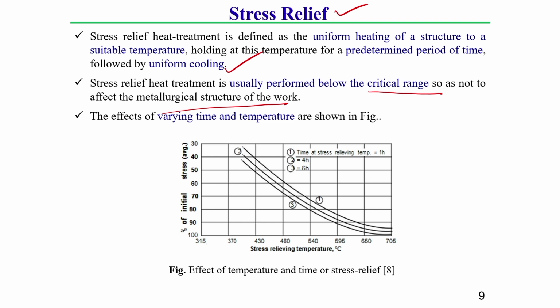Here I am showing a curve. You can observe that the higher the temperature, the higher the relief of initial stress. What does this curve represent? The first, top curve represents a holding or soaking time of 1 hour, the second curve represents a holding time of 4 hours, and the third curve represents a holding time of 6 hours.